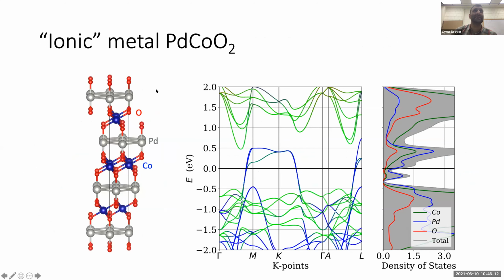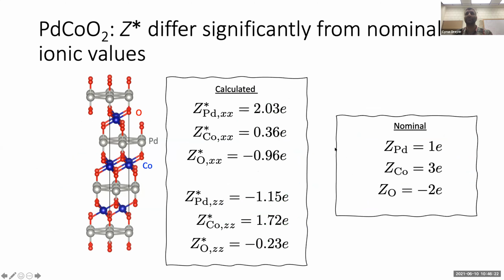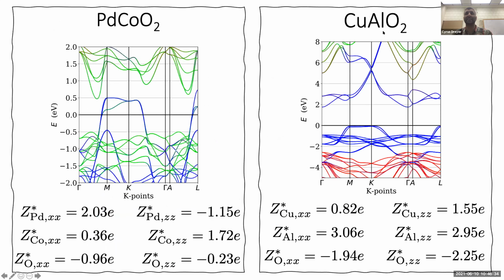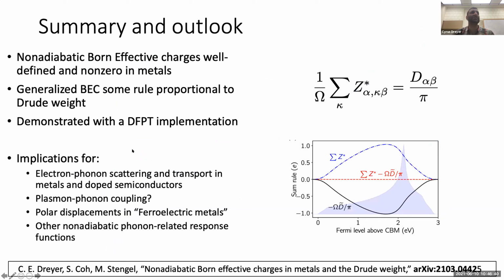Okay, so the last thing that I'll just mention in one minute is palladium cobaltate. It's a metal intrinsically, and I think I'm just about out of time, but I'll just say that the calculated Born effective charges we find differ significantly from what we'd expect the nominal charges to be. And we can confirm these nominal charges by looking at an insulating material that's quite similar. And yeah, we can discuss this more in the Q&A if you're interested.